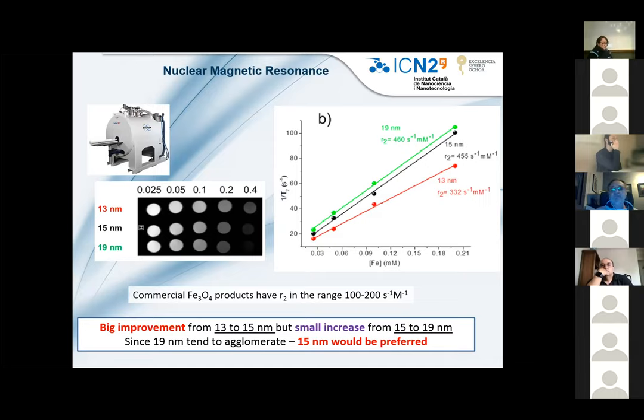Then we did some nuclear magnetic resonance experiments on these particles, and we see that at 13 nanometers, the R2 value is 330. But when we increase by just 2 nanometers, this value increases from 330 to 455. And if we increase further to 19 nanometers, the change is very small. Here is the transition: these samples are colloidally stable, while these ones eventually precipitate.